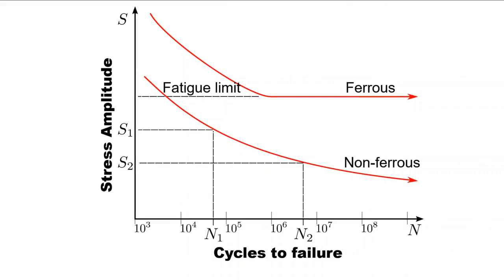The way that fatigue behavior for design purposes is tabulated is by relating some stress characteristic of a fatigue test versus the cycles to failure. While I've shown stress amplitude on the vertical axis, this could also be maximum stress or some other facet of the test regime. There are two different types of fatigue curves. One that is associated with a ferrous material which has a fatigue limit, and for non-ferrous materials, one that does not demonstrate this fatigue limit. Instead, fatigue lives are characterized by an endurance limit. That is, for a characteristic stress, there will be a number of cycles to failure. The endurance limit for N1 cycles, for example, is S1, and S2 for N2. For ferrous materials, if the stress is kept below the fatigue limit, then it will be able to withstand an effectively infinite number of cycles.